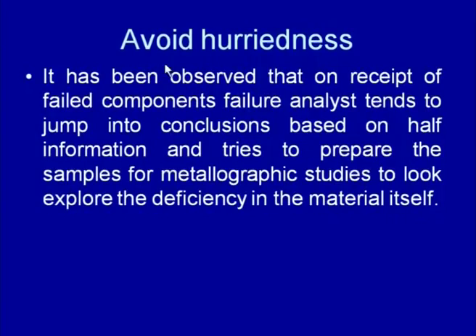And because of this, one precautionary note is that hurriedness should be avoided, because it has been observed that on receipt of the failed component, the failure analyst tends to jump to conclusions based on half information and tries to prepare the sample for metallographic studies to explore the deficiency in the material itself. So, this is the common tendency: the failure analyst jumps to conclusions through half information and tries to look into the deficiency in the material itself through metallographic examination.